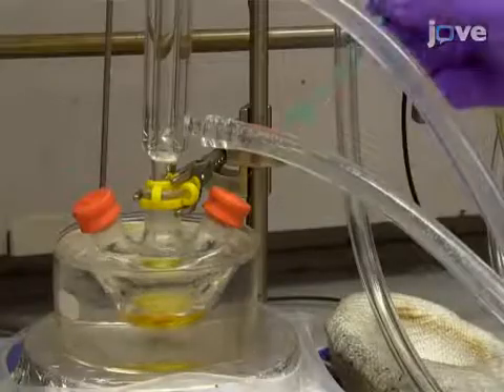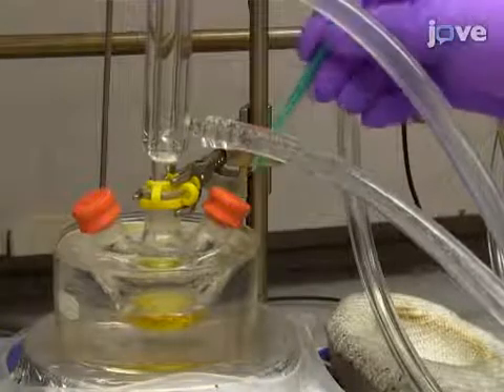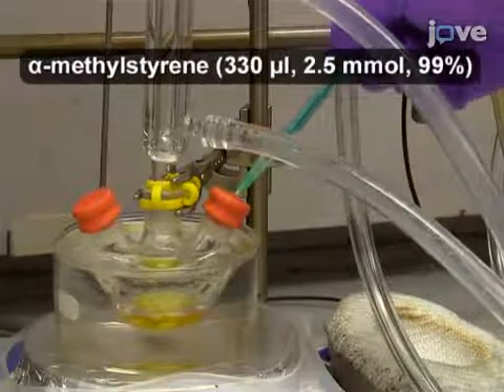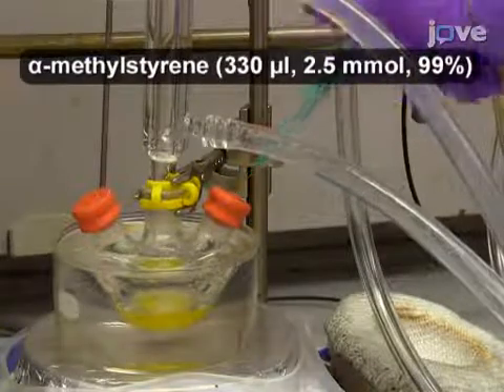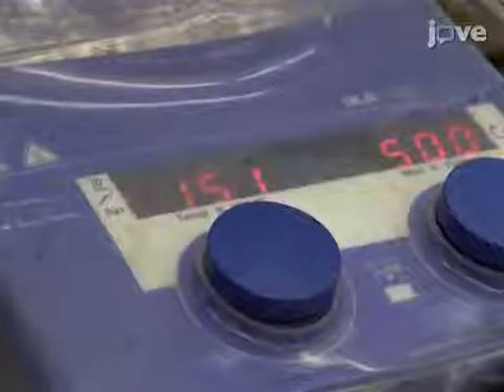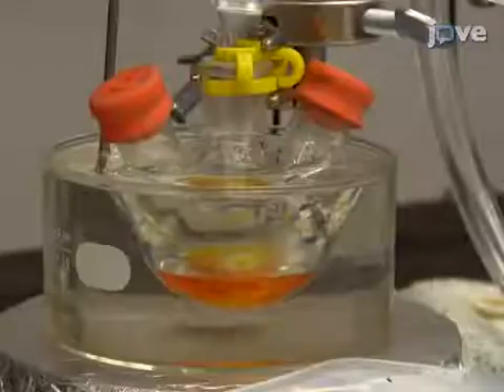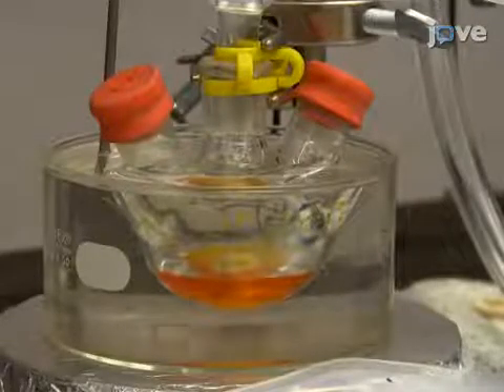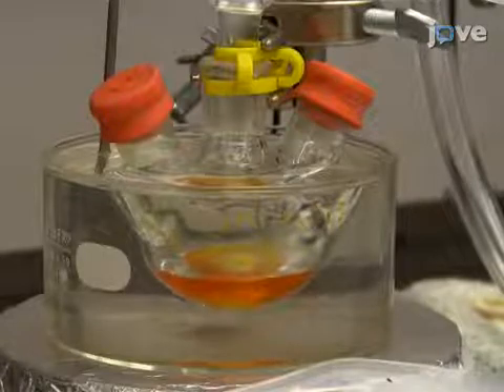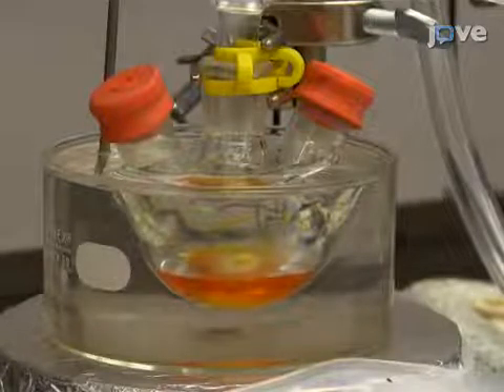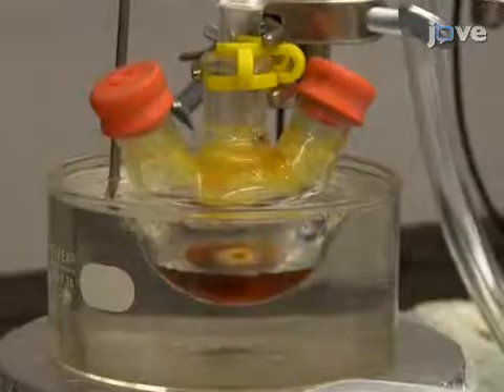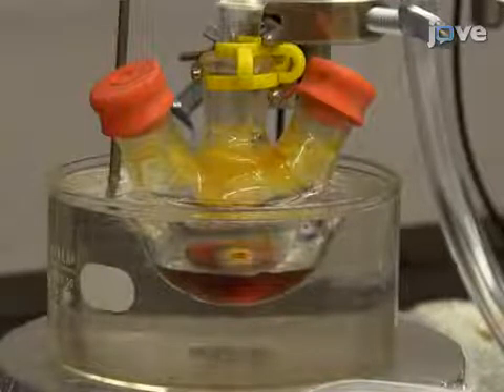Once all of the sulfur has dissolved into the liquid, immediately inject alpha-methylstyrene into the solution. Heat the solution to 185 degrees Celsius with stirring at 500 rpm for 10 minutes. As the copolymer forms, the solution will change color from yellow to orange, finally producing a deep red color.